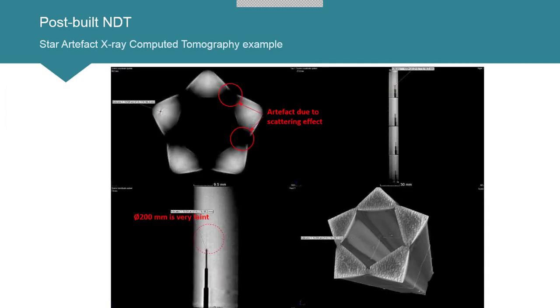And then next I'm going to show you just one example, because otherwise it would take several hours to show you all the results that we have, some of which will be included in the standard. This is X-ray CT, showing different projections of the artifacts which were scanned. There were 1, 2, 3, 4 stacked stars as you see on the top right, and then the 3D image on the bottom right, and then just a slice where those vertical cylinders were concatenated, and we can see that the 3 largest ones were easily detectable. The one at about 200 microns started to get